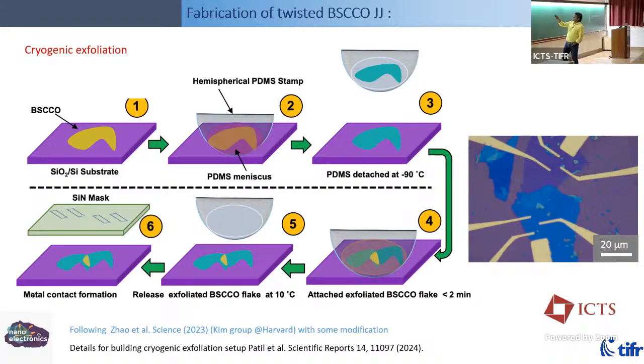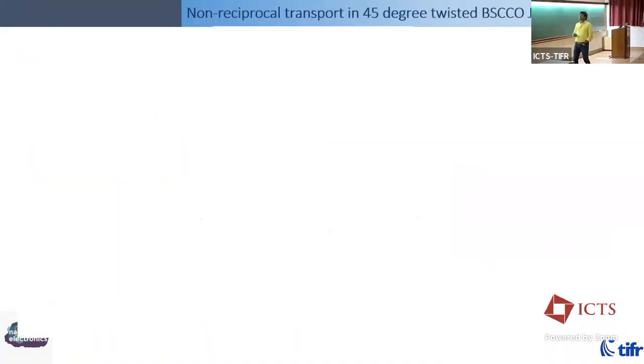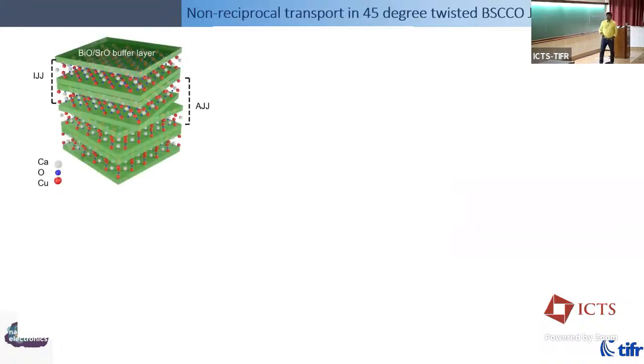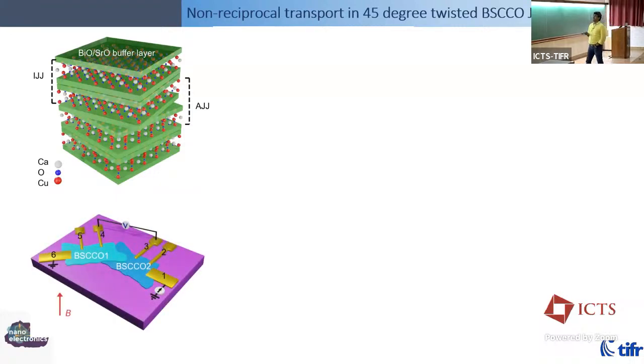So at the end of it, it's the same flake. You peel off the same mother flake, and you place it back. And this is the region where the Josephson junction is formed by putting it back. And these are the many electrical connections that we need to make the measurements. Okay, so this is sort of the cartoon of this device. So it's not monolayer, because working with monolayer, with this kind of gymnastics of cutting, peeling, putting back, makes the yield especially low. For the interfacial Josephson junction, it doesn't matter whether it's a few nanometers or a unit cell. So we work with about 10 nanometer thick flakes.